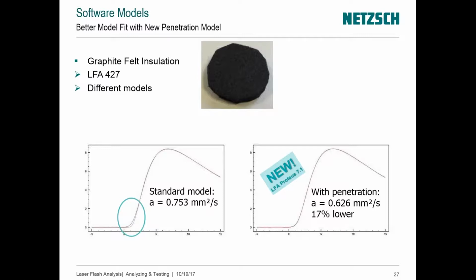On the left-hand side, that's what would happen. You will see that if you are using a standard model, at the beginning stage of the temperature excursion, the data fit will not be as expected. In other words, you do see a significant discrepancy between the data and the best possible standard model. Standard means a model that does not account for penetration or for porosity. So you see how it will be.